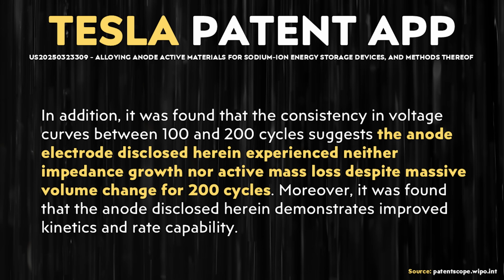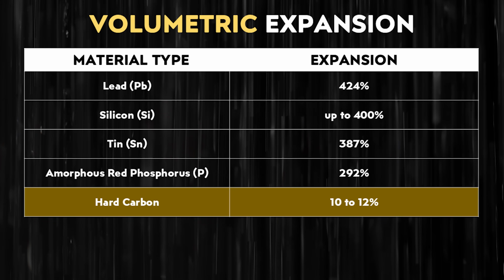In addition, it was found that the consistency in voltage curves between 100 and 200 cycles suggests the anode electrode disclosed herein experienced neither impedance growth nor active mass loss despite massive volume change for 200 cycles. Moreover, it was found that the anode disclosed herein demonstrates improved kinetics and rate capability." So unlike silicon, it looks like the expansion with these alloys in the anode is not causing the same damage as you would normally expect. So this is really exciting.